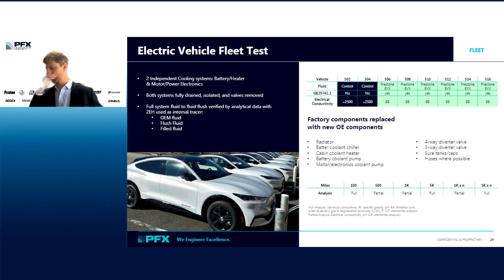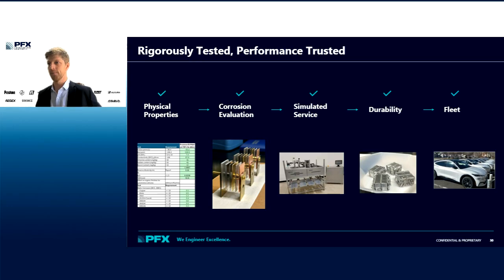But what we see here is that our process for setting up these tests is very controlled. Our data is very repeatable and reliable. We have a sampling schedule to make sure to capture all of the minute changes, from electrical conductivity to percentage of glycol, your inhibitor levels, your glycol degradation products. We monitor all of these things and plot them throughout the entirety of the test. This is another thing that not all coolant manufacturers do, that Prestone is very proud of and leads to the superior products that we put onto the market.